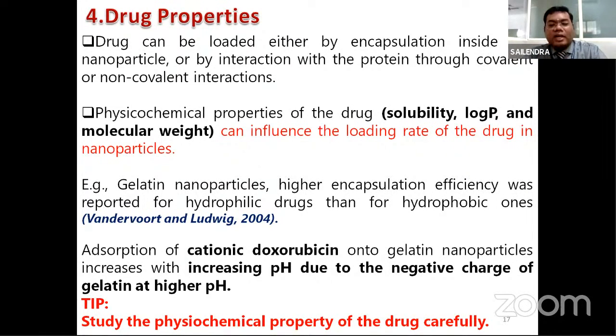With gelatin nanoparticles, you achieve higher encapsulation efficiency with respect to hydrophilic drugs compared to hydrophobic ones. So depending on the type of drug molecule, sometimes your protein nanoparticle is chosen, or there are certain nanoparticles where you can functionalize the surface depending on the type of drug you want. So usually gelatin nanoparticles are preferred for hydrophilic drugs. So water-loving drugs will be attached on the surface of these gelatin nanoparticles, but it is not recommended for hydrophobic drugs.